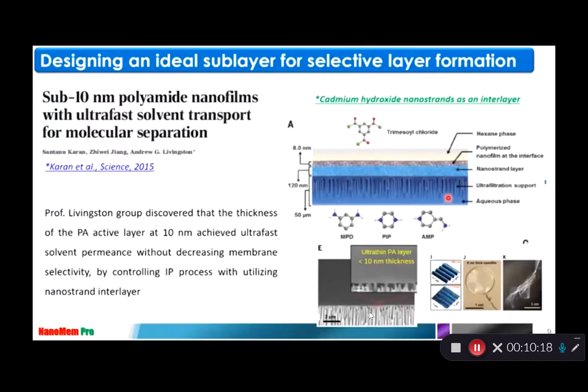So you can see the support layer for general ultrafiltration, like PSF or PES, and then the nanostrand layer. They utilized a nanostrand layer as an interlayer between the support layer and your selective layer. And then the selective layer is the typical polymerized nanothin film at the surface, like MPD-TMC or PIP-TMC, and they try to separate some organic solvents. So this is their study. They found that a polyamide layer of less than 10 nanometers, ultra thin, will give very high solvent permeance. That's our inspiration. We try to control this very thin polyamide film layer,